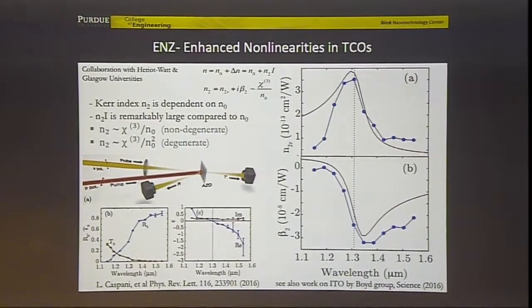We visited the ECE. I know there are some activities related to zinc oxide. If you dope it with aluminum, and depending on how much metal you put into it, you could have this crossing point where epsilon goes from positive values when it's dielectric to negative values when it's metal, at any point you want. It simply depends on the doping.